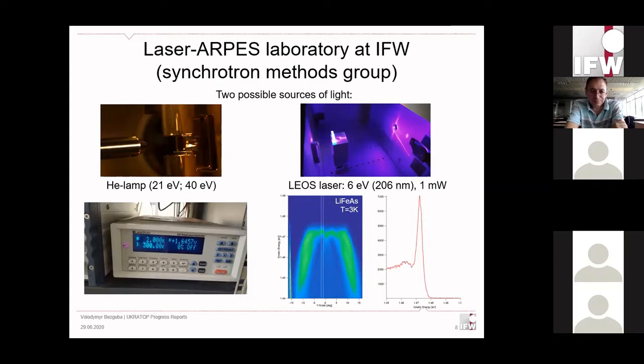And like Andrei said, we can achieve temperatures as low as 2 Kelvin. From one point of view, it's a bit of cheating because 2 Kelvin is not very stable, but we can hold it for a minute, which can be enough to get a spectrum. So it's actually a very good temperature for the laboratory. And here in the bottom right corner, you can see an example of such a spectrum measured with the new laser, and it has a resolution of about 2 meV.